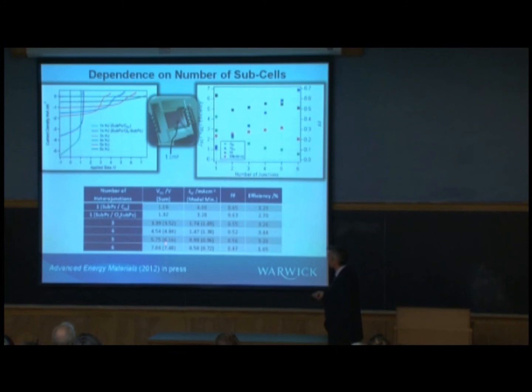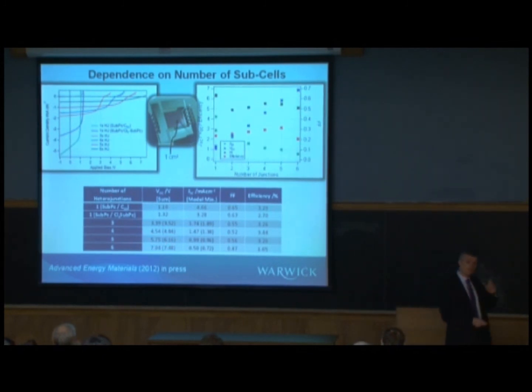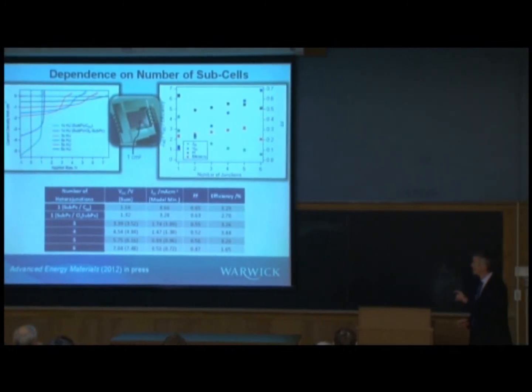So the results are summarized here. A 3-junction cell is about 3.4 volts. A 6-junction cell is now over 7 volts. And the numbers in brackets are the ideal voltages you would get if you summed up the voltages of the independent cells. So it's pretty close. You're seeing a slight reduction, but it's pretty close to the ideal value. So that's a very high voltage in a single cell.